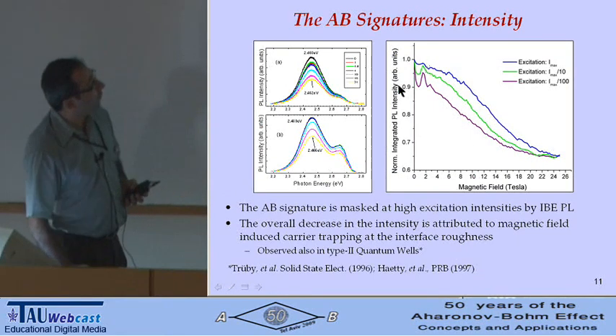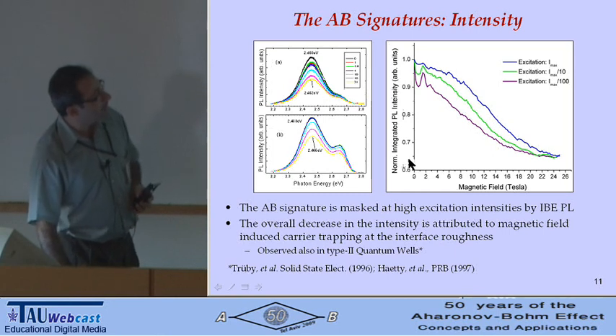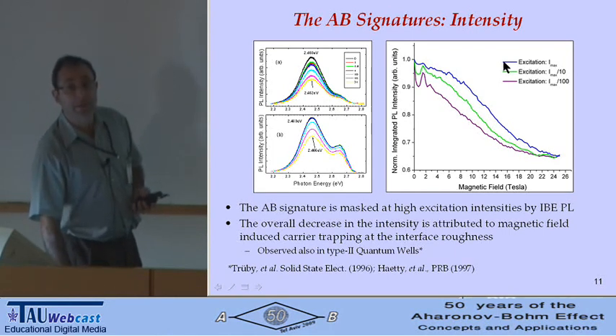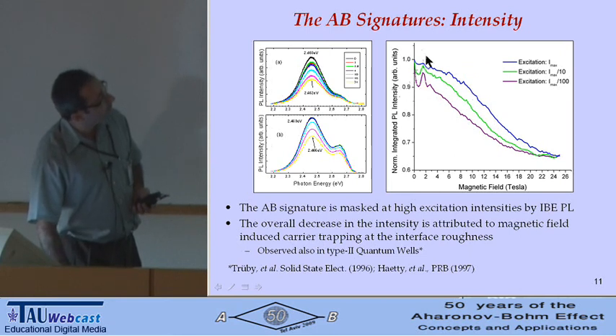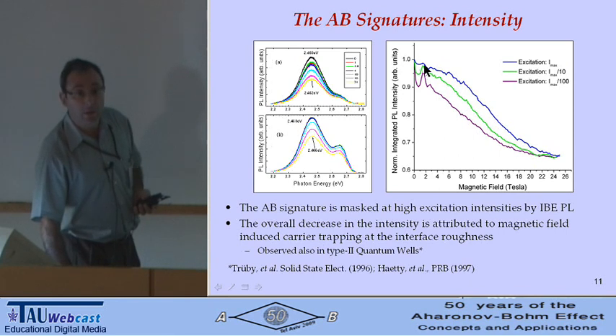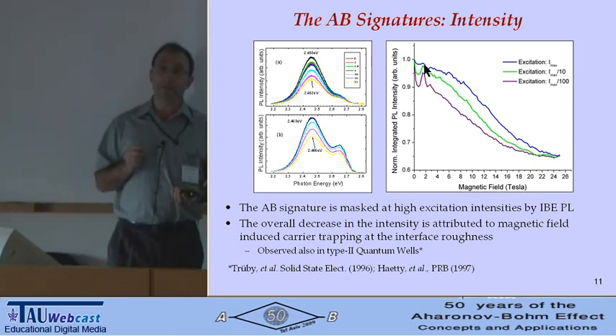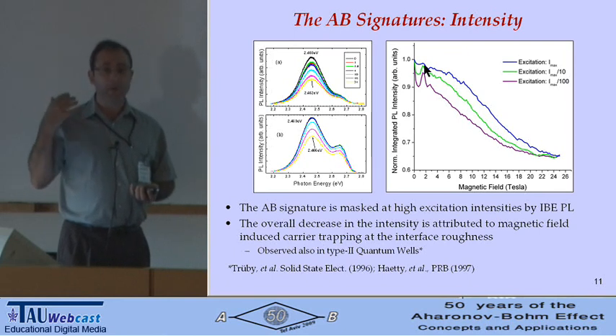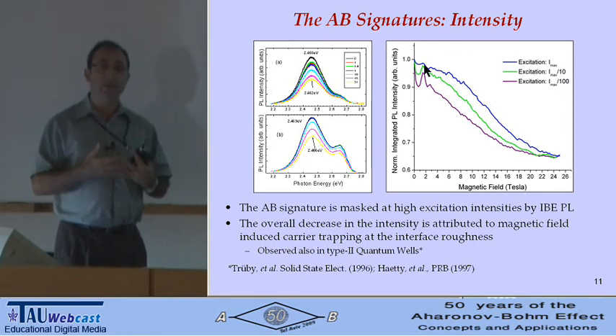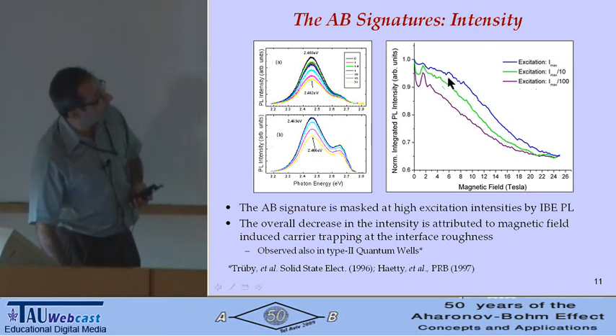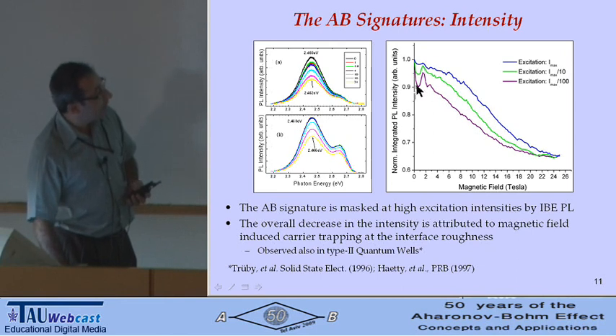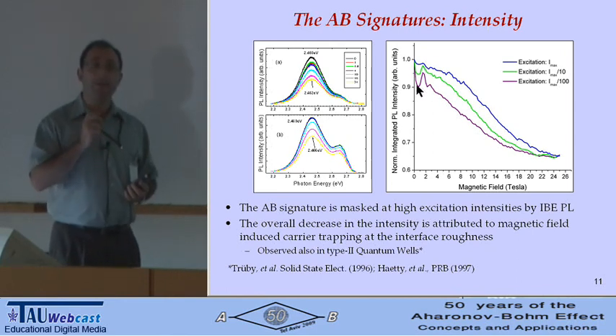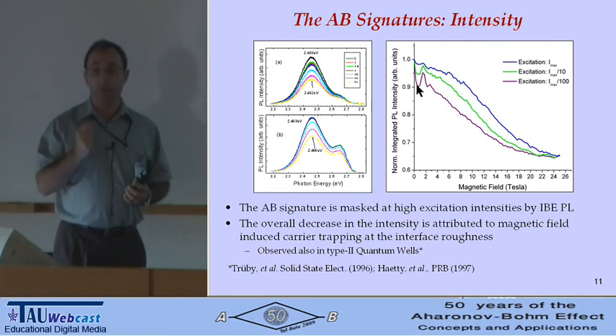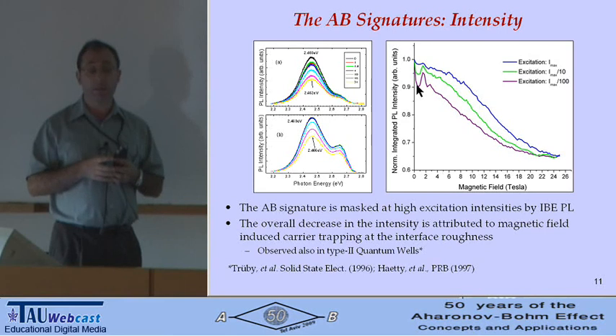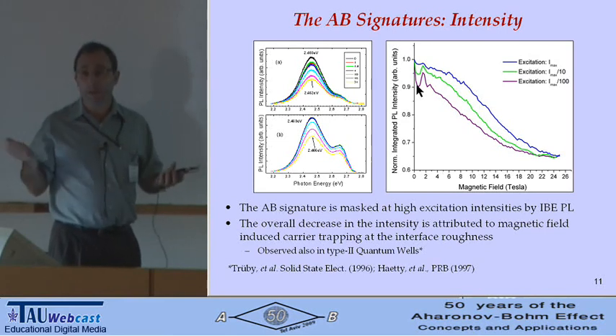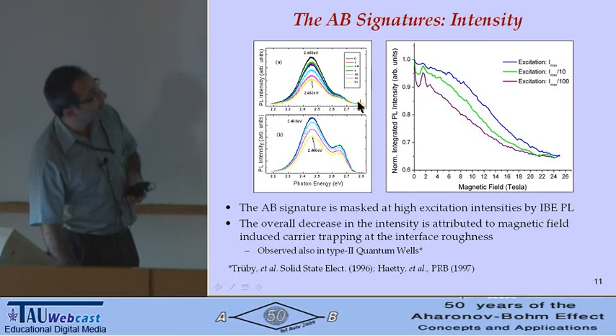So these are measurements of photoluminescence related to quantum dots in the magnetic field at different excitation intensities. It's interesting that at high excitation intensity, we see only a very small wiggle here. However, this pertains to specific properties of our system, because it has a strong isoelectronic bound emission, which you have to suppress to see emission from quantum dots, which we did by reducing the excitation intensity, and we see these nice oscillations. It's important to point out that these are quantum dots, not quantum wells, because in quantum wells you don't have a closed orbit, so you will not see the oscillations. And people, of course, have done magneto-optical measurements on quantum dots. They saw the overall decrease in intensity, but not the oscillations.